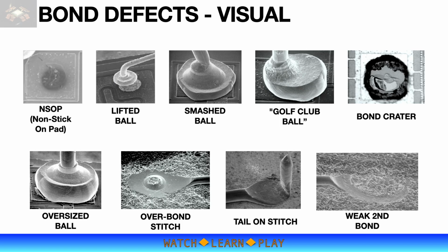Visually, it looks weak because of the small and thin fishtail. The weak bond can be confirmed through wire pull tests. Also notice that the capillary impression is light and incomplete. About half of the capillary impression is missing. An incomplete capillary impression is an indication that the transducer is not mounted properly. This will also affect first bond quality. To address the stitch shape of a weak second bond, optimizing capillary design will certainly correct the problem.